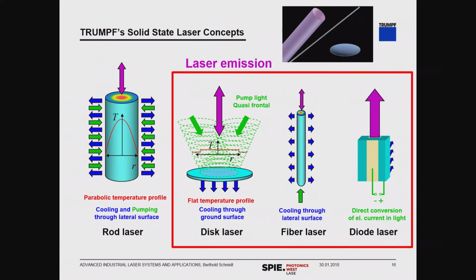Being a diode person, I know that to improve the power level of a laser diode, you normally reduce the confinement factor, bring the internal losses down, and then enlarge the footprint of the laser device to have better cooling. You can do the same thing with a fiber laser and a disc laser: reduce doping concentration, enlarge mode size and diameter, and for fiber, for instance, enlarge the length of the active fiber. On the disc laser, you're enlarging the ratio of surface to volume. That's why we use a thin disc laser.